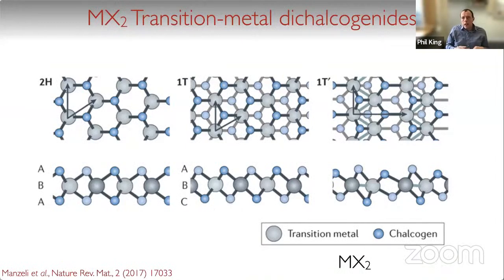Okay, so we've already heard in the conference about some of the members of the transition metal dichalcogenide family, and I'd like to then continue considering this system here. And for what I talk about today, I'll be talking mostly about the so-called 1T family of these systems, where we have a transition metal that forms a triangular lattice here, and this transition metal sits at the center of a chalcogen octahedron. So just like, say, the perovskite structure, for example, except here these octahedra are tilted over so that they're edge sharing, and then you have these octahedra joined along their edges in the plane.